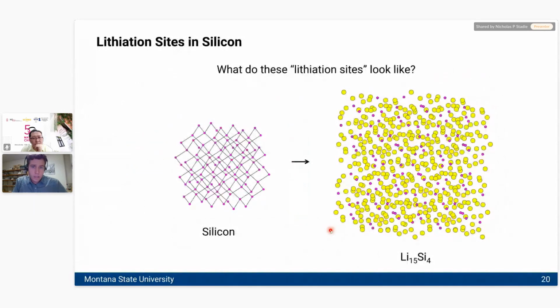So what's the cause of this problem? It's not just us not being able to make a good quality electrode. It really is something inherent to silicon in the way that it works. And the answer to this question is there is no such thing as a free lunch. So while on paper silicon looks like a fantastic anode to replace graphite with, it has a better gravimetric capacity. It has even a better volumetric capacity of lithium than even bulk metallic lithium. This leads to some really serious differences in chemistry.